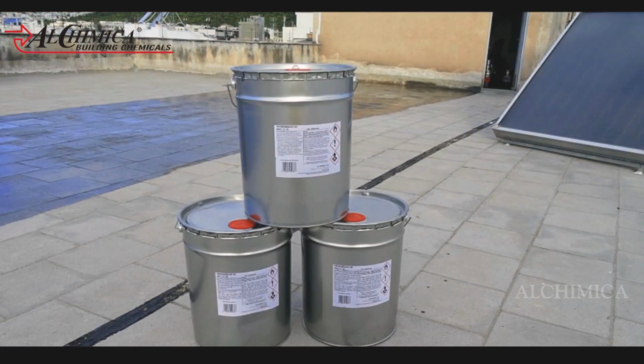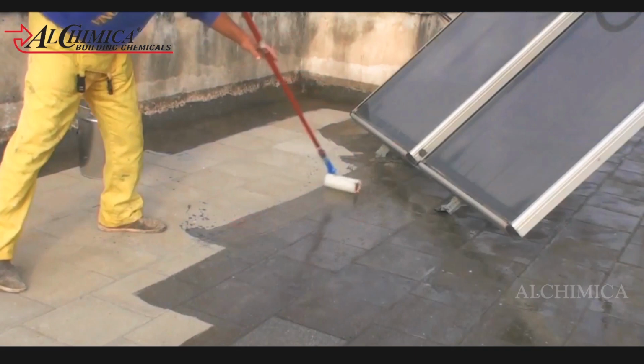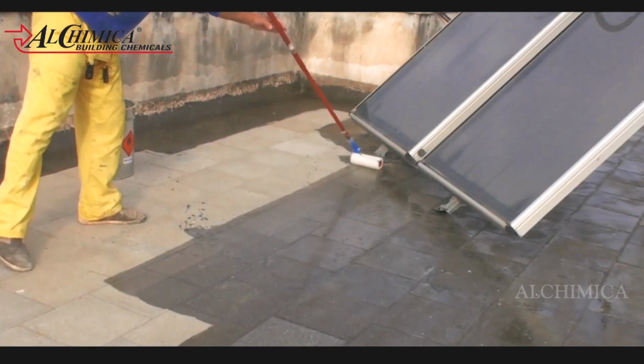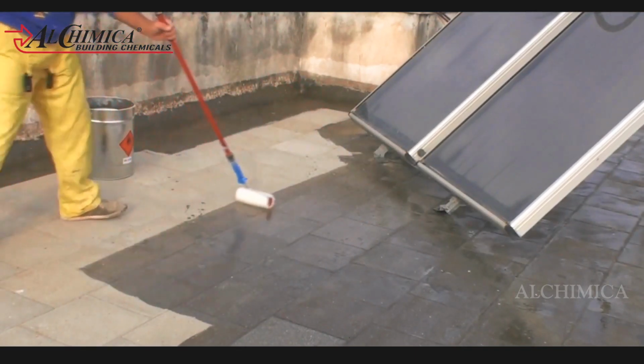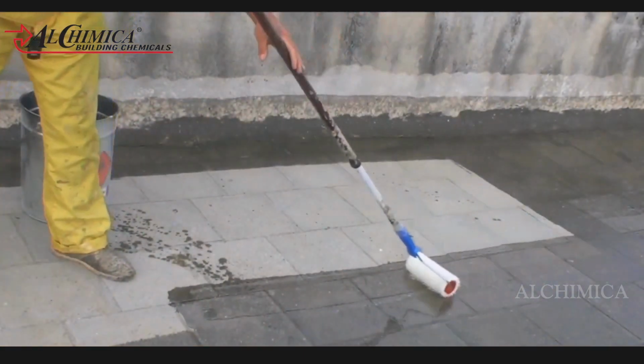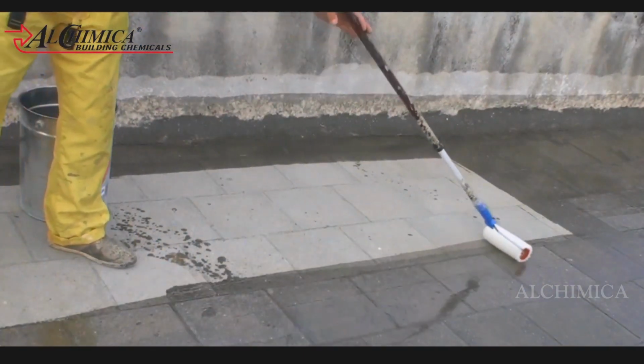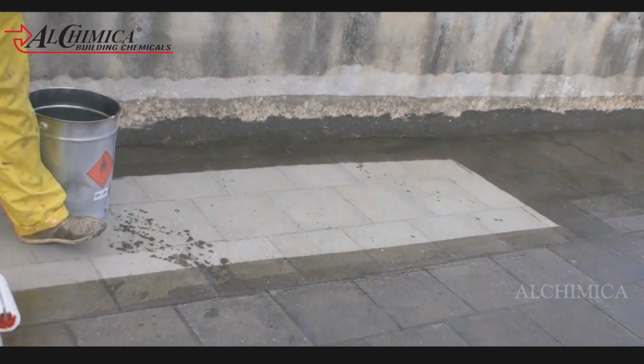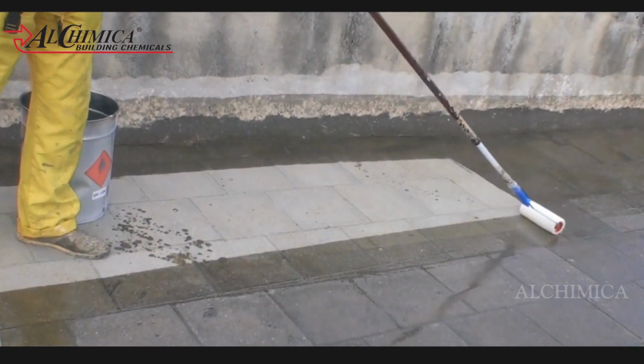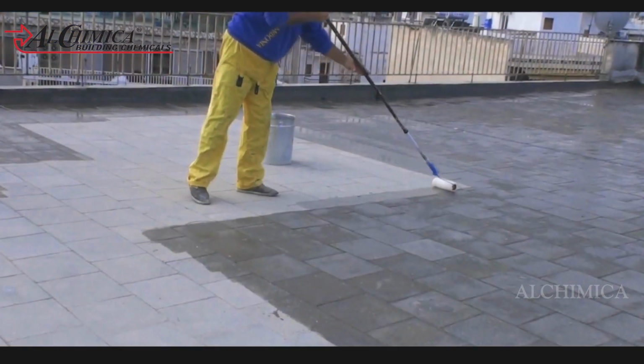The coverage of this primer depends on the surface condition. However, the standard recommendation by the manufacturer is 10 square meter per liter per coat. In certain site conditions, multiple coats of Microsealer 50 primer are also recommended.